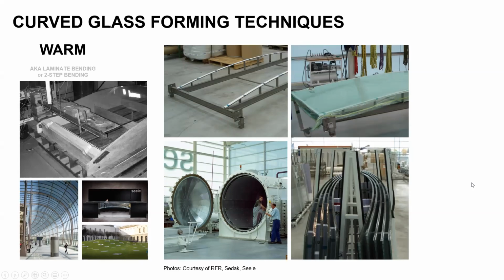Warm bend glass consists in piling up sheets of glass and interlayer. You just stack them on top of each other, throw them into a vacuum bag and clamp it into some sort of jig that you then roll into your autoclave and laminate as such. So when you've pushed the glass in place, you've elastically deformed it, and this is how the glass is shaped. But when the laminate gets out of your autoclave, it's the interlayer that prevents the glass from coming flat again. And so each glass transfers loads to the interlayer to the next glass over, etc.